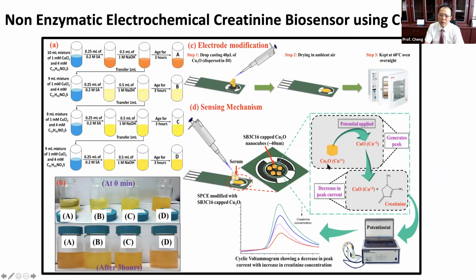The sensing mechanism is that when we apply a certain potential, the Cu2O will oxidize to CuO. And this CuO will react with creatinine. Then the Cu2O on our sensor will disappear into the solution. So if you have more creatinine, it will react with more Cu2O, and then we will see a decrease in the current.